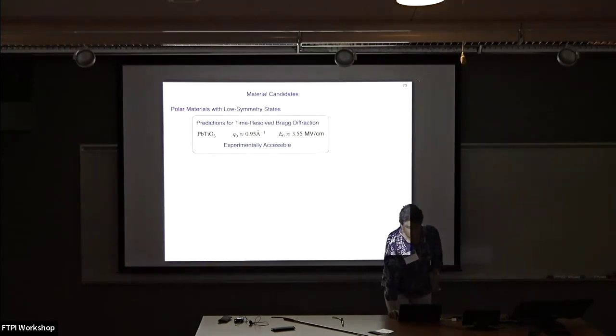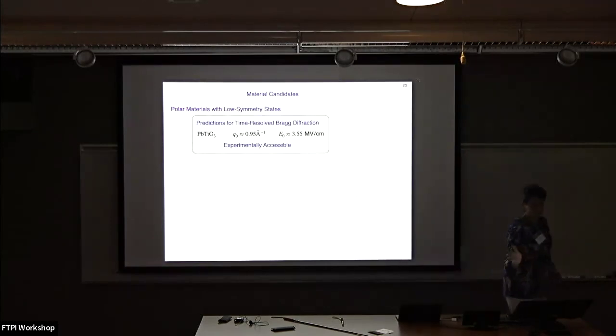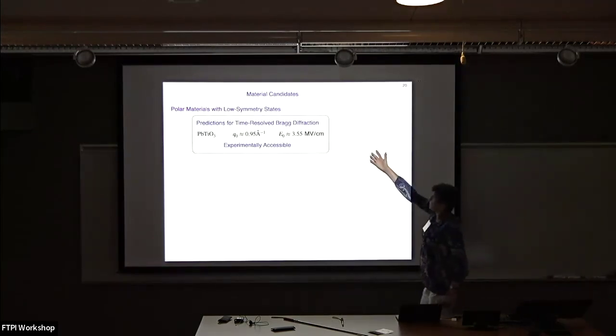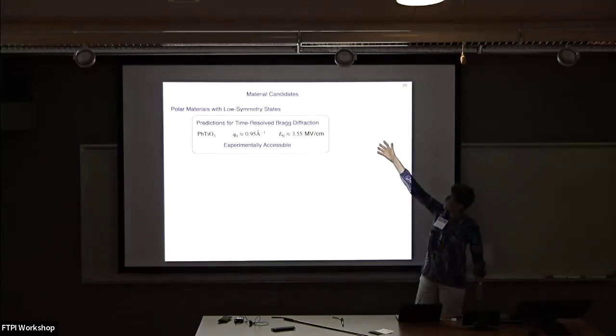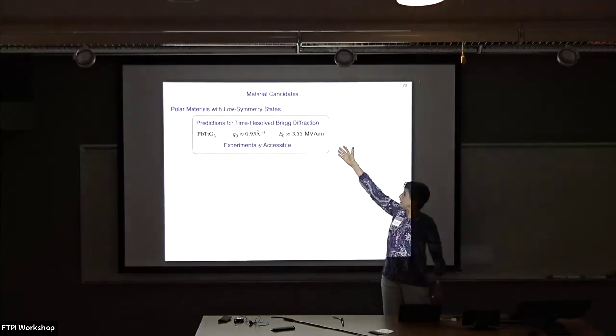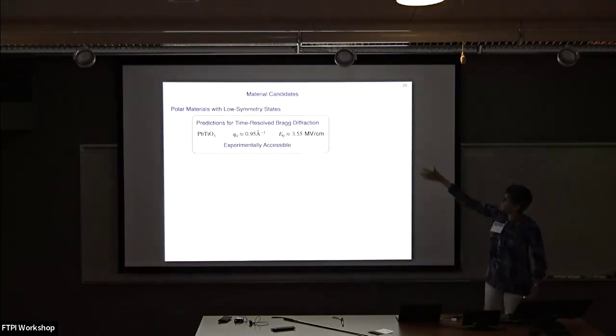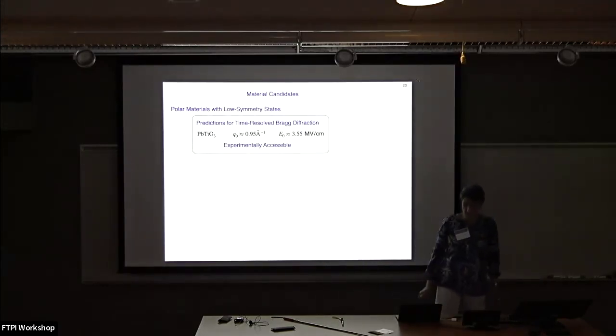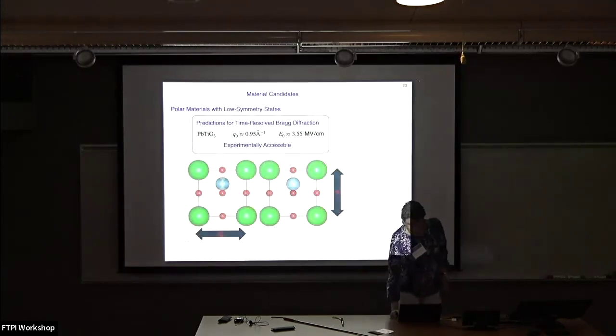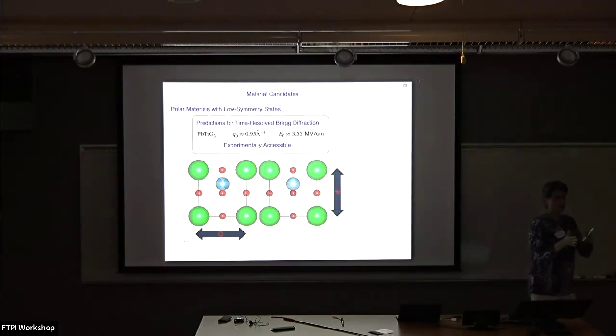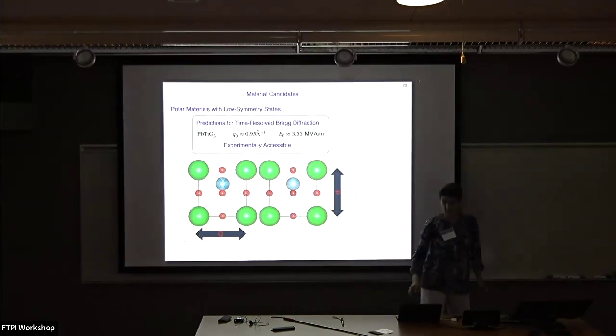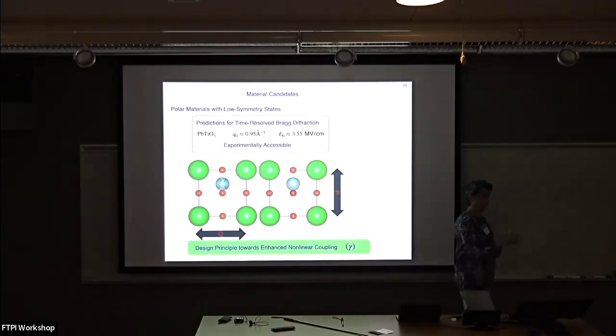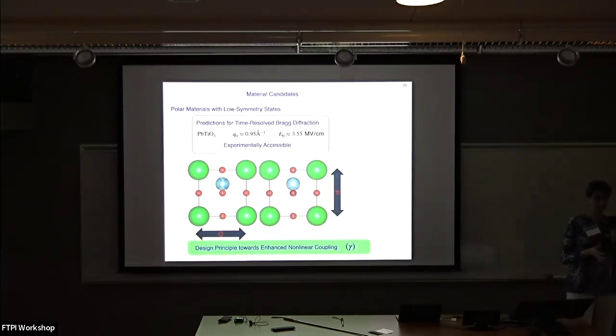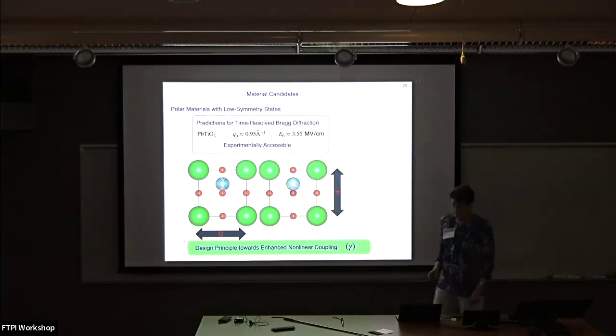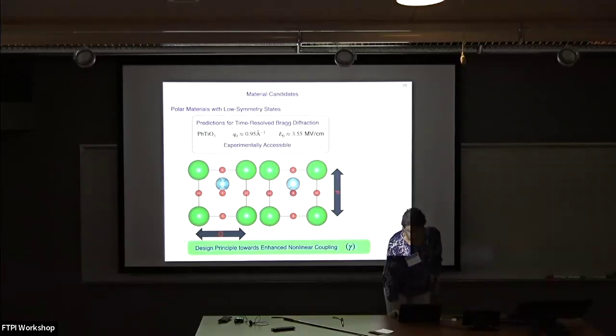Okay, so let me just get to material candidates, polar materials with low symmetry states. We wanted to put in some numbers for lead titanate. We have the coupling, a reasonable electric field fluence to get this, and a reasonable Q0. We actually think for lead titanate the modes are both longitudinal. We actually think that you can have an enhanced coupling if in fact the modes involve the same atom. I'm happy to talk about this more, but that's something that we would like to explore.